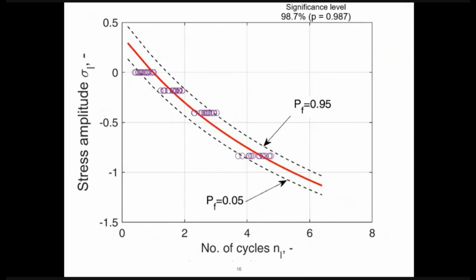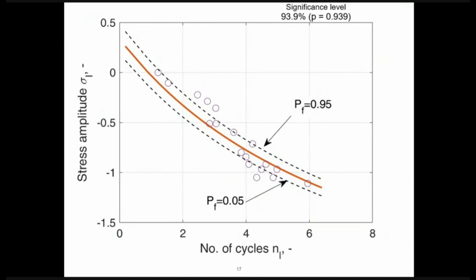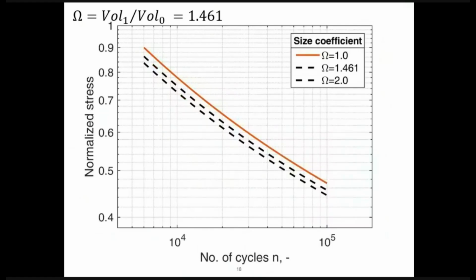And getting to the results with this Castillo normalization model curve, those are the calibration results, those 80 specimens here. The red line is a median of the model, and the percentiles, in this case 5% up and 5% down, are the dotted lines. So this was the calibration, so obviously it fits with 98.7% significance level, and the test results that we use to check the model have a slightly lower significance level of almost 94%, but you can see the results here on the same lines. And this is the representation of the different SN curves, where the red one, the orange one, I think, is for the calibration.